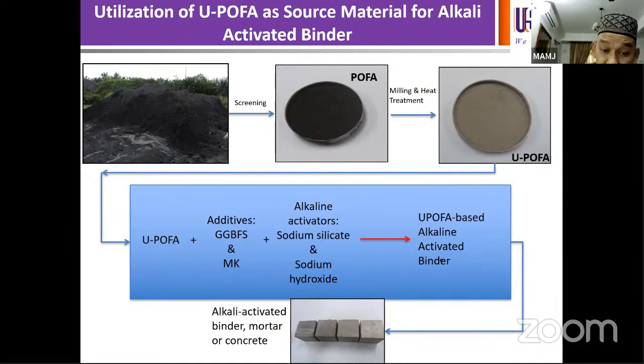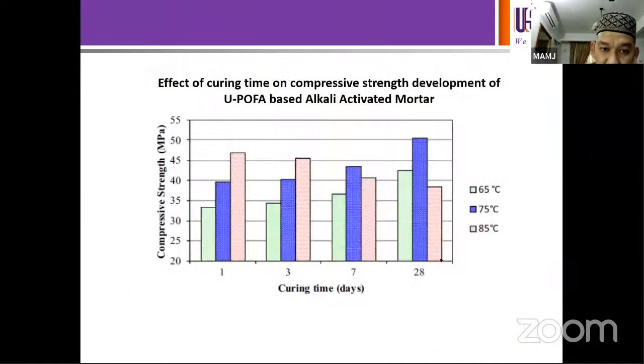The research is still very much ongoing, and there are quite a lot of interesting outcomes from this research, which will be reported in the form of papers, etc. So here are just some results: the effect of curing time on compressive strength development of POFA based alkali activated mortar, at different curing temperatures of 65, 75, and 85 degrees Celsius. We are seeing that probably 75 degrees Celsius is more or less the optimum if you want to obtain maximum strength at 28 days.